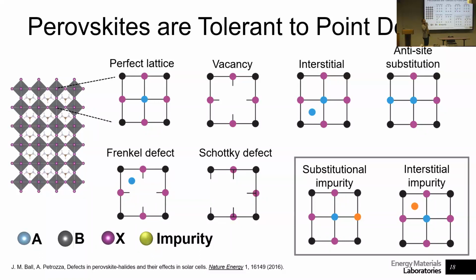Because silicon solar cell people might know this better than anybody. You need to have like 9 nines of purity in your material in order to avoid recombination dynamics that happen in the material. So point defects are very important in any semiconductor material that you're trying to develop. This can be vacancies, interstitials, and so on. Substitutional impurities is a big one, especially in industry. You don't want an iron contamination in your silicon ingot line because that iron implants itself and creates deep traps in the middle of the gap, and that creates a lot of trouble for your solar cell.